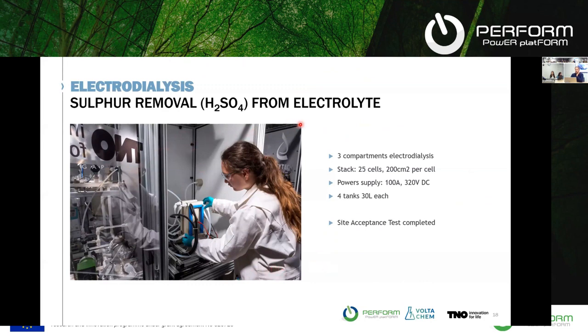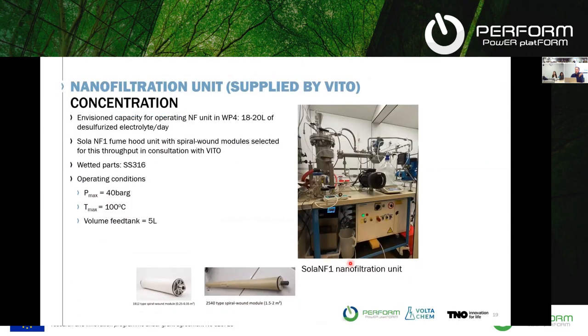When we look at the first step, electrodialysis, we need it because we need to remove sulfur, or in general, sulfuric acid, from the electrolyte. Here, again with EasyTech, we built a pilot setup with a 25 cell stack, where we can carry out the electrodialysis and remove most of the sulfuric acid from the electrolyte. So in a way, we are concentrating our maleic acid a bit more. After that initial electrodialysis,